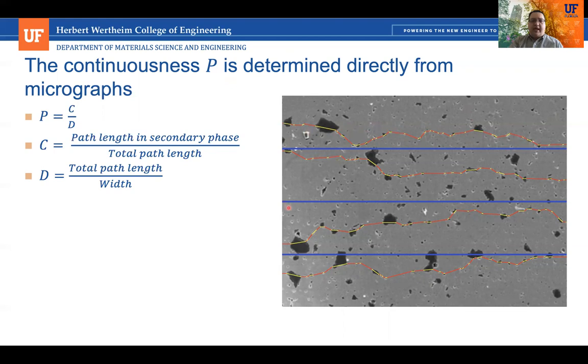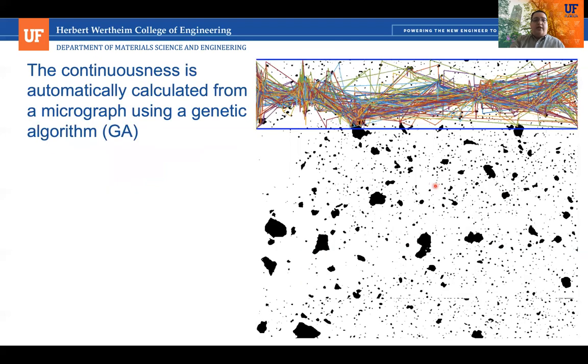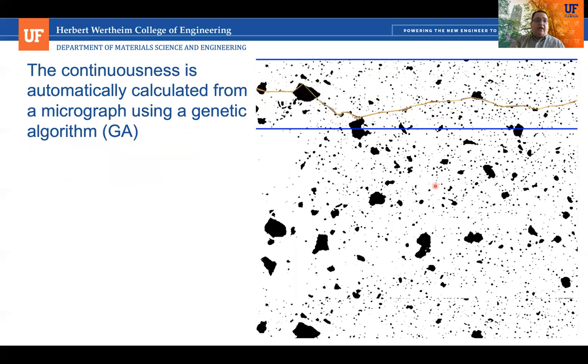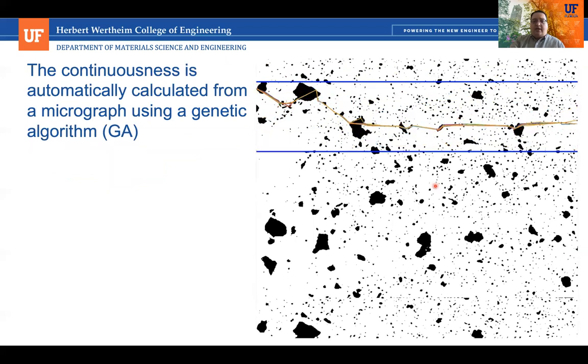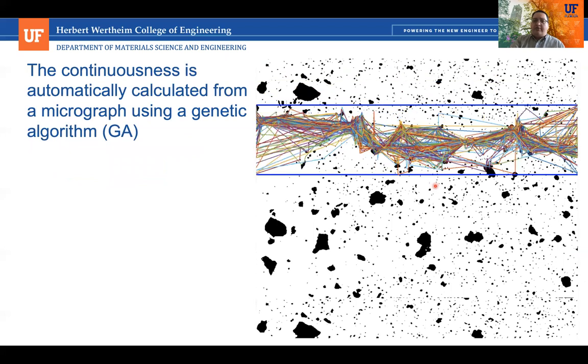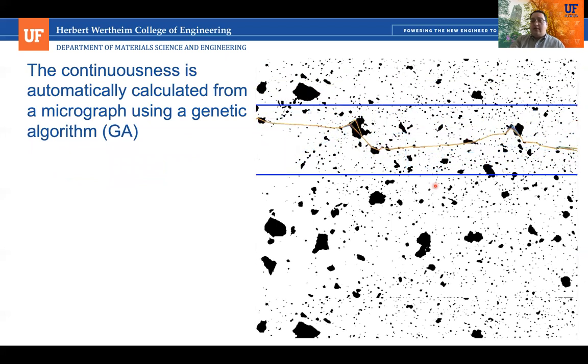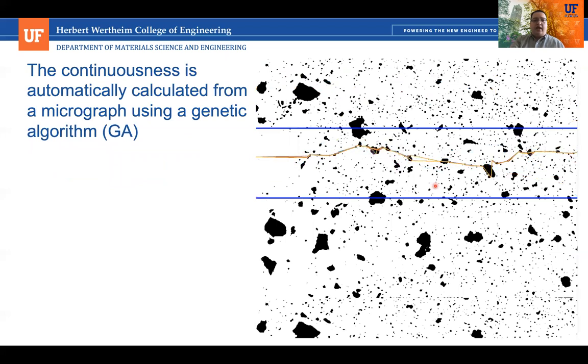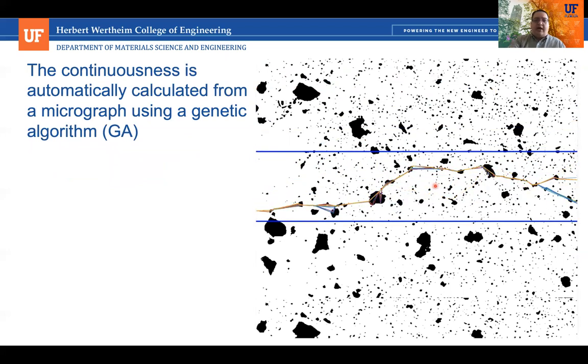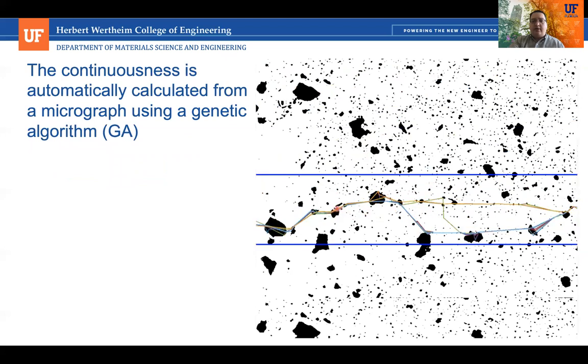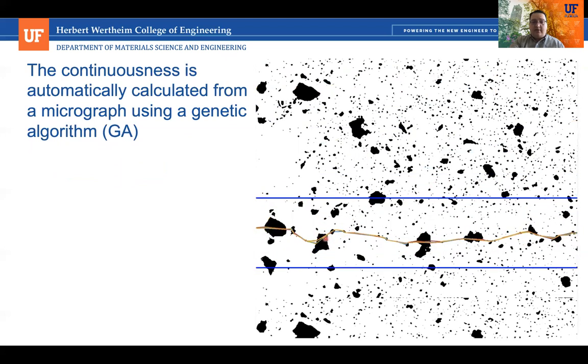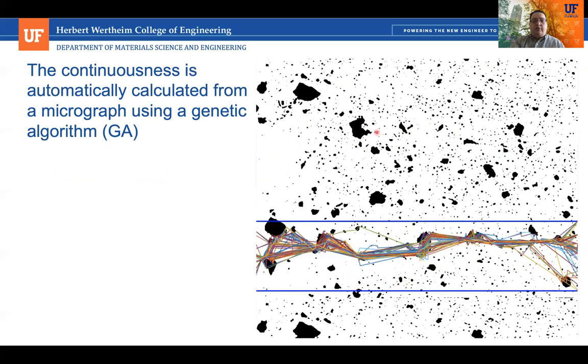However, having to do this by hand, drawing these lines and trying to stay within the other phases, is a burden and sort of a pain, but it can also lead to a lot of dependence on the user. And so we've also developed a genetic algorithm that takes a binary image that's either black or white, where white is the UO2 and black is the high thermal conductivity additive. And it actually draws these paths, and it tries to maximize the continuousness of each path using this genetic algorithm.